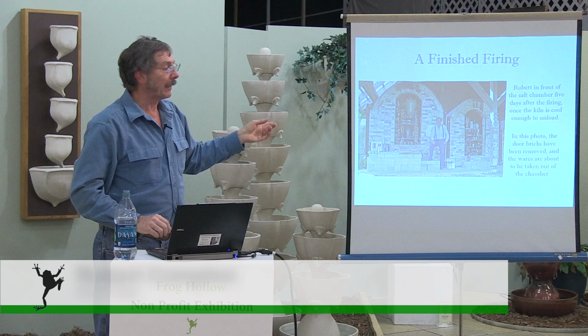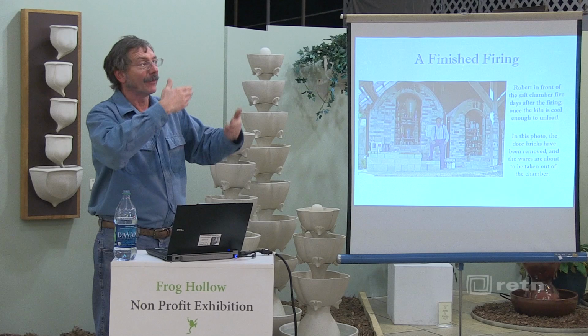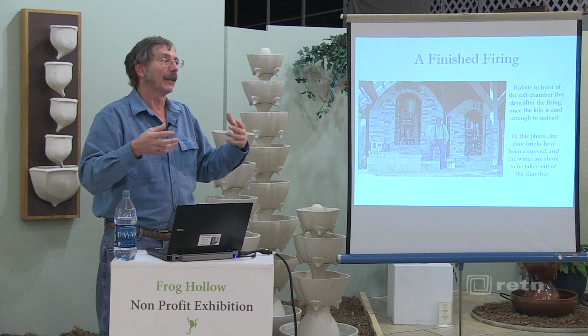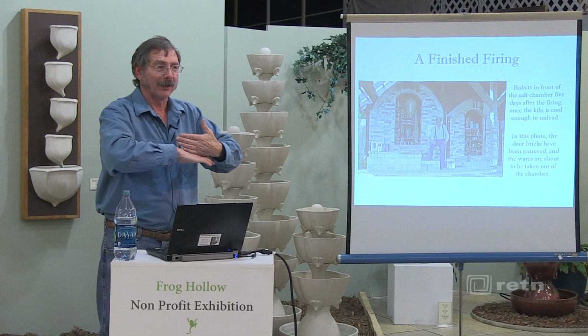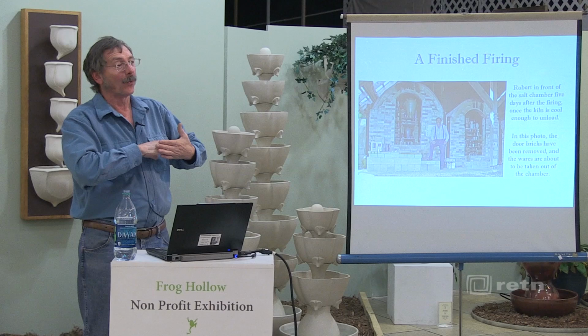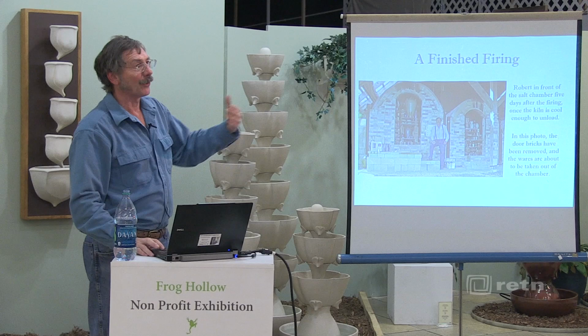They wear out, and the ones facing the fire side wear out pretty quickly. So I'm rotating. I dip bricks after each firing into a wash of aluminum hydrate, almost like kiln wash, to help prevent so much penetration. And then after a couple firings, I'll flip them one side to the other so the other side's getting hotter. And then when they start to look like they're going to shrink on me, I move them one course in. So they're getting moved out toward the outside layer with three courses of them. It would take me about 10 years before I've worn out all my door bricks.